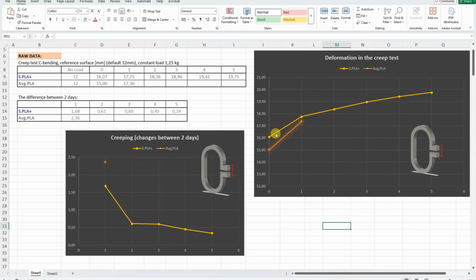And we can see bigger deformation on the Super PLA Plus compared to the average PLA, but this is only the initial deformation. The creeping is the difference between 2 days. Now I'm already recording first 2 days, and we can see that here the average PLA has bigger creeping compared to the Super PLA Plus, and something similar we can see on the bending test too.